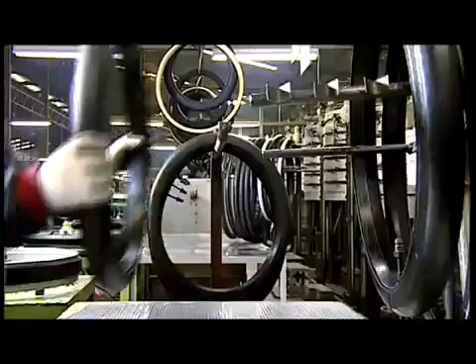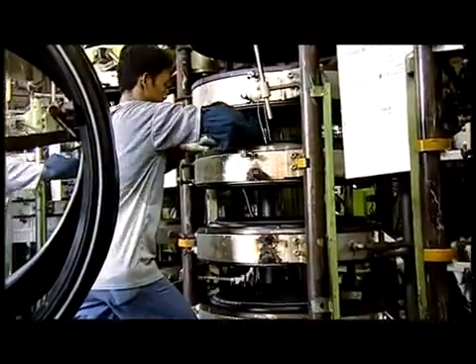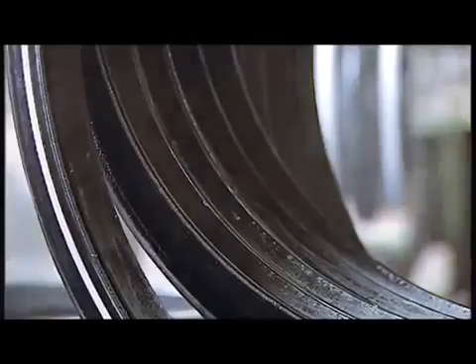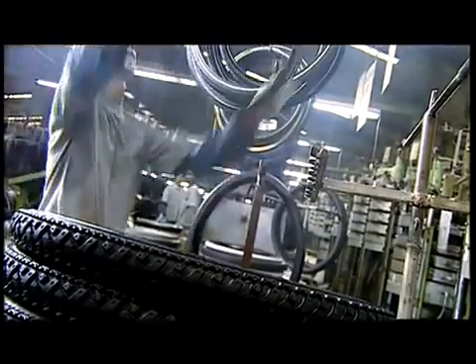But first, a heating tube is inserted inside the raw tire. Finally, it is ready to be vulcanized in the tire press, like a giant waffle iron, at around 170 degrees for 5 to 6 minutes. After each cycle, 6 tires with their special Schwalbe treads are born. As the tire now has its flexible characteristics, only after vulcanization is it possible to describe it as rubber.